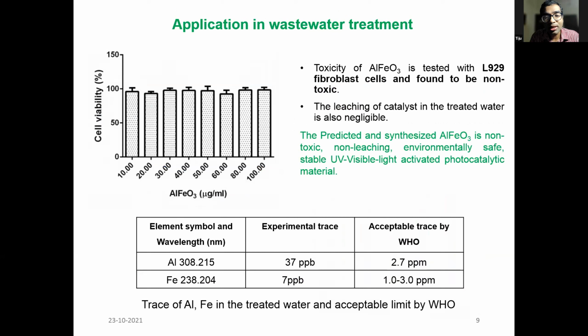You need to also think about whether these particles, when they are used for water treatment, end up leaching into water, as a consequence giving rise to concerns that might be of relevance to further treatment. But it turns out that this is perfectly leaching resistant. There's no leaching at all. And in fact, we carried out certain biotoxicity tests in our biotech department in Professor Mukesh Doble's lab. And we found that these materials are totally leaching resistant. Next, please.